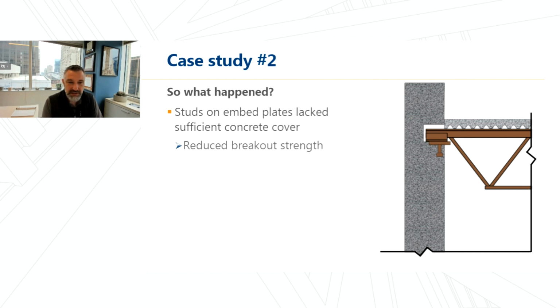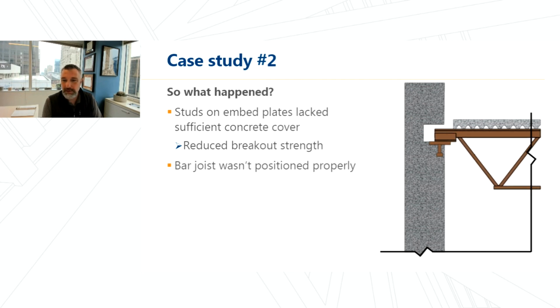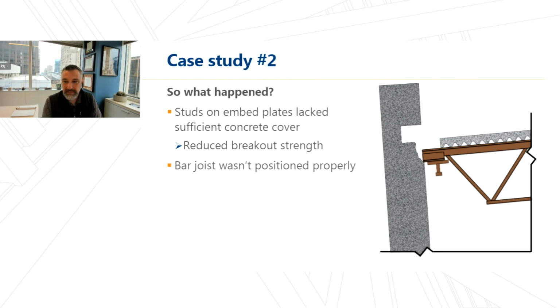embed plate was constructed to be outboard of the intended location, and this resulted in a significant reduction in breakout strength. In addition to that, the joists were not positioned properly, so they did not have enough concrete to bear on. They were positioned actually outboard of the wall. And so the failure mechanism here involved a breakout of the concrete surrounding the embed plate, which caused the joist to deflect and push the wall out.